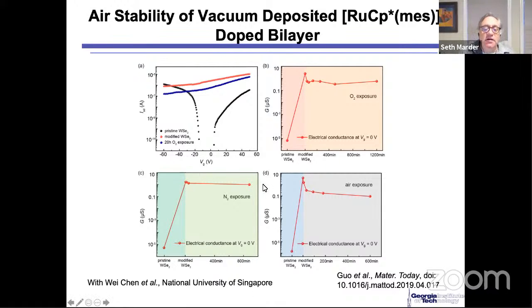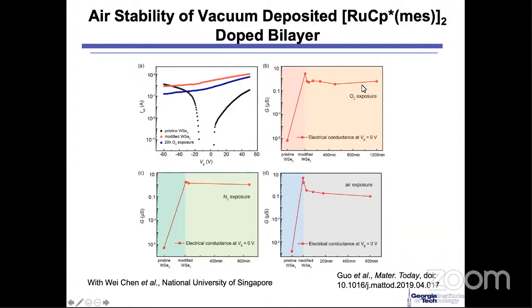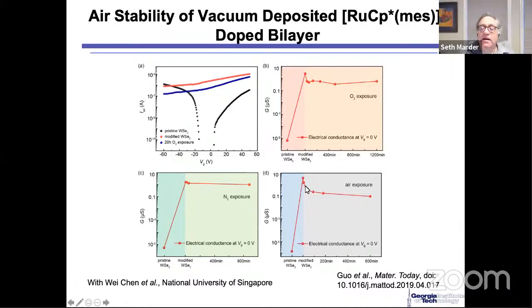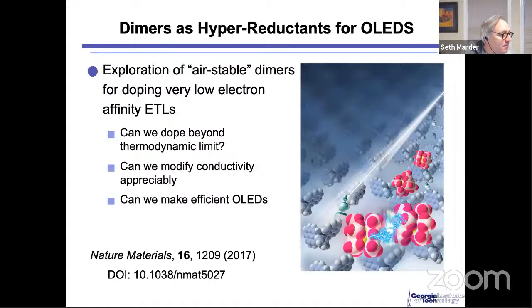And in nitrogen, it's basically flat after a long time. After oxygen, it changes a little bit. And in air, again, it changes maybe an order of magnitude or so, but it basically stays pretty nicely doped and pretty conductive, even after 10 hours in air. So this is a simple way to start playing around with the electronic properties of these two materials.